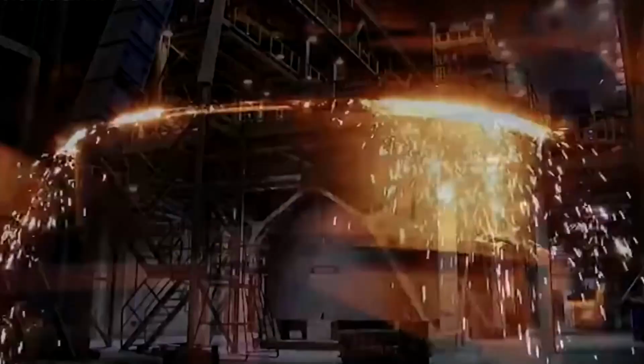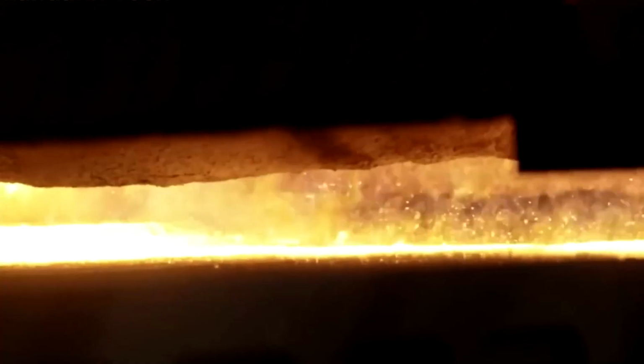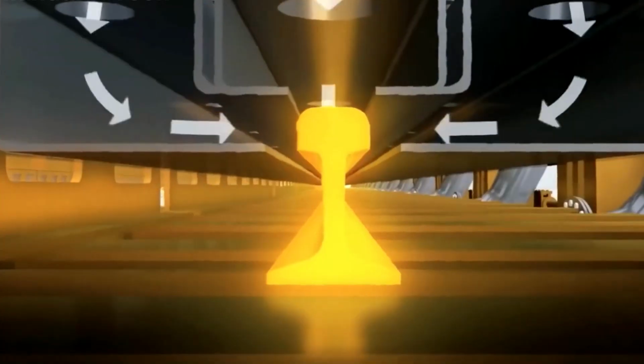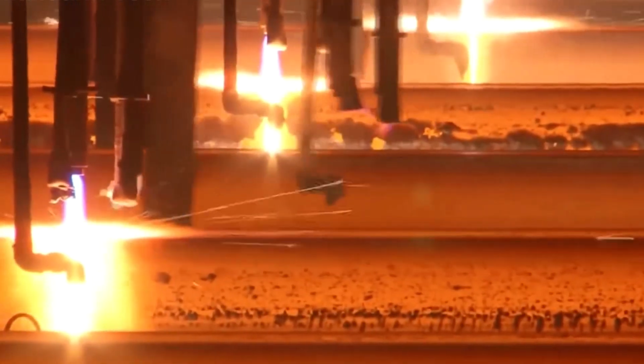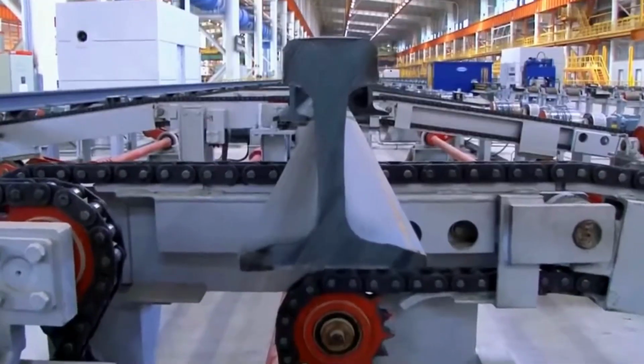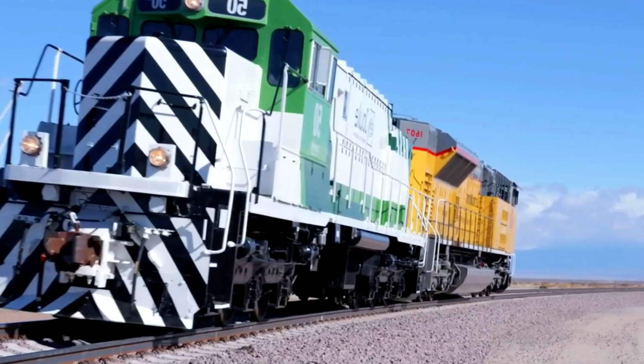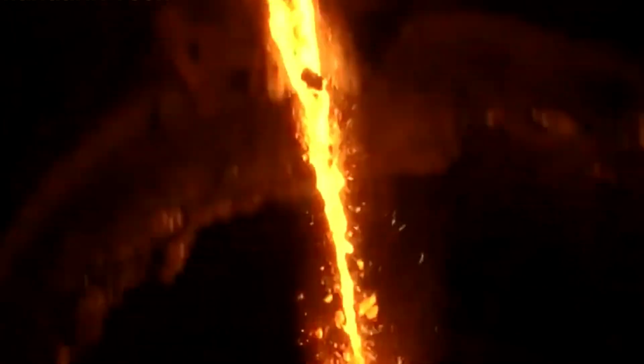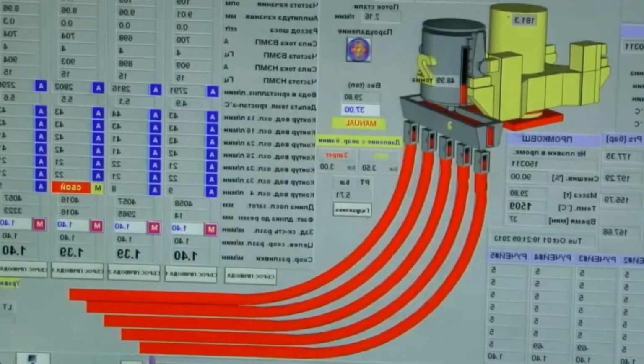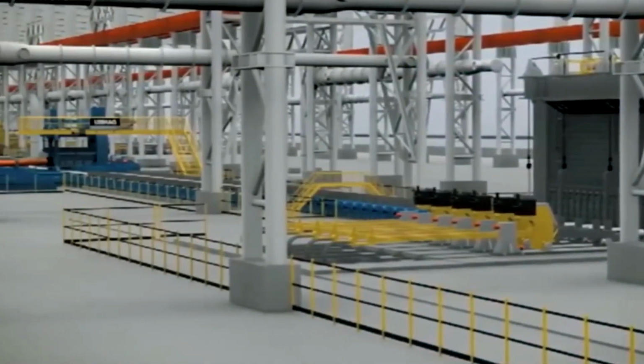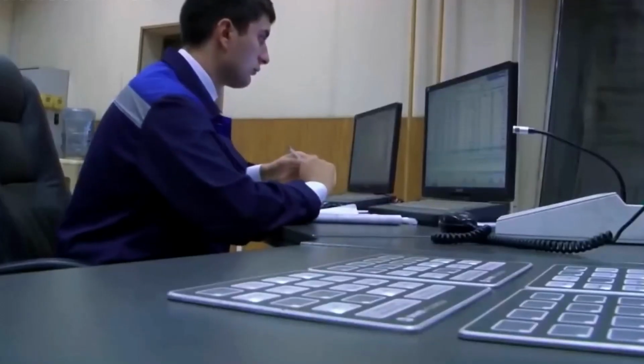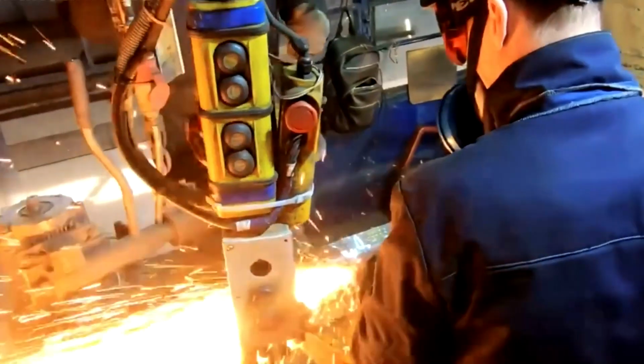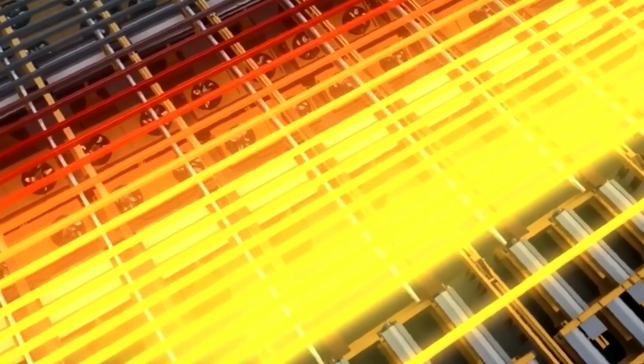The entire operation is monitored through a central control panel. Finished rails transfer to the automated inspection area, where high-speed cameras and optical sensors scan the entire surface at microscopic resolution. Ultrasonic and X-ray systems examine the internal metal structure, automatically rejecting any rail that fails to meet specifications. Random samples are tested using tensile machines, compression rigs, and Rockwell hardness testers to evaluate load-bearing capacity. Each rail that passes inspection is laser marked with a traceable identification code, ensuring full production transparency before shipment.